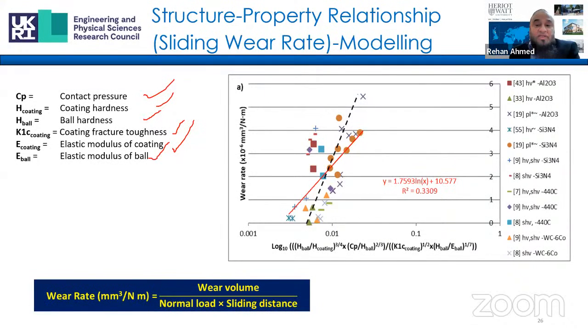And the problem lies in the way we define wear rate itself. See, the wear rate has a force term, which is the normal load over here. And this alludes the wear performance because the influence of a given load is geometry dependent. For example, a load of 25 Newton on a steel ball of 10 millimeter diameter is not the same as a load of 25 Newton on a tungsten carbide or a ceramic ball in terms of the contact pressure. Now, even for the same ball material, as the load changes, the contact pressure changes non-linearly. So hence, we can include the influence of geometry in the wear rate calculation by replacing the force term with the Hertzian contact pressure CP term.